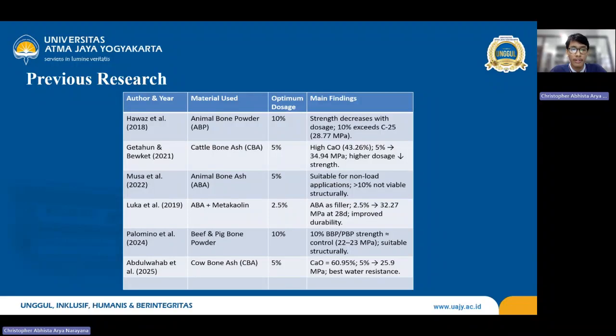Then these are several previous studies about the incorporation of animal bone. The first is the research by Hawaz et al., in which they used animal bone powder with an optimum dosage of 10%. As a finding, the strength decreased with the doses, while the 10% exceeds the control compressive strength. Second is Getahun & Bewket in 2021, in which they used cattle bone ash at a 5% substitution level. They found that the bone ash has a high calcium oxide content, and 5% substitution can reach 34.94 MPa, while a higher dosage decreases its strength.